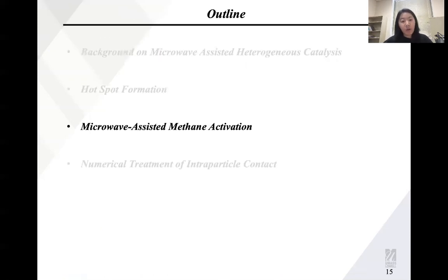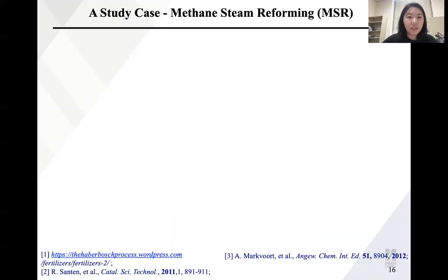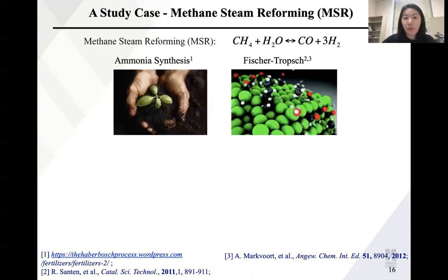Then the next part we want to know is what role this hotspot plays in heterogeneous catalysis, mainly gas-solid heterogeneous catalysis. We use a case study, which is the methane steam reforming reaction. Why do we use this case? Because 95% of the hydrogen in the United States is generated from this methane steam reforming reaction, and the hydrogen can be used for ammonia synthesis for agriculture. The syngas generated from methane steam reforming can be directly fed into the Fischer-Tropsch reaction to generate long-chain hydrocarbons. And this reaction itself is very important because it has broad application in the States.